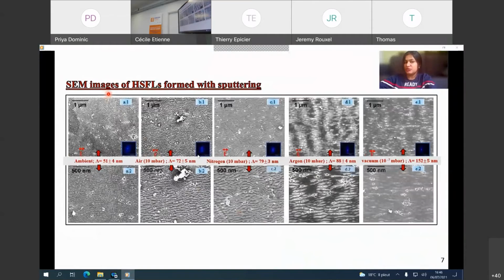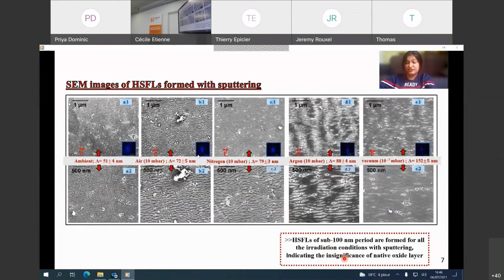And then we have some images of HSFLs formed with sputtering, so without any native oxide layer. And here also we can see HSFLs with very small periods for all the different gaseous conditions, and it indicates the insignificance of any native oxide layer for the formation of ripples. So we have the same images with and without sputtering, which indicates the insignificance of ambient air and native oxide layer for the formation of HSFLs.